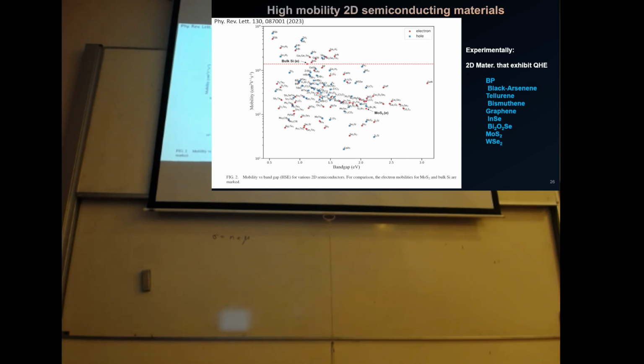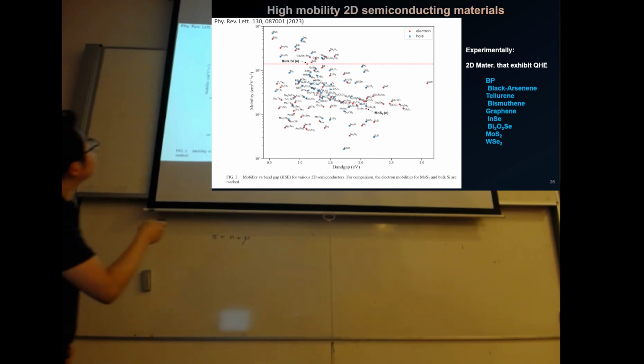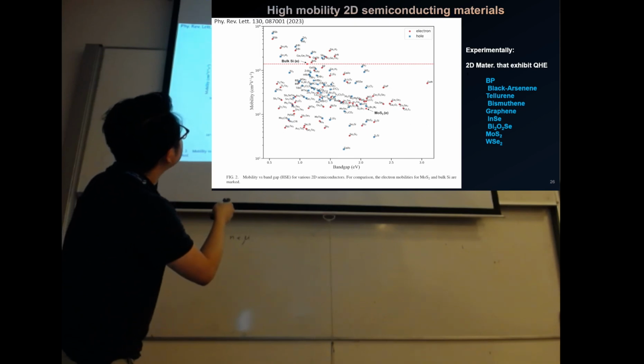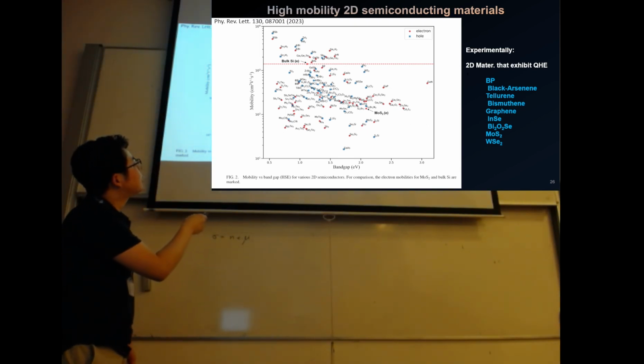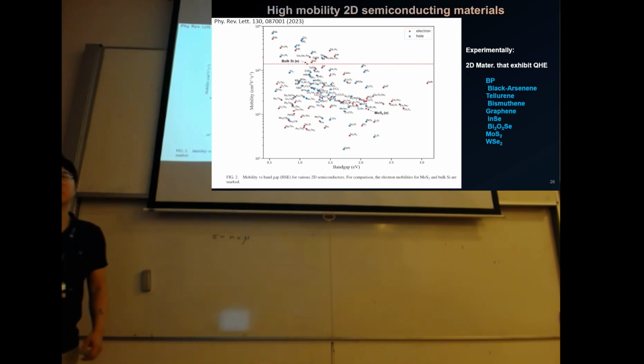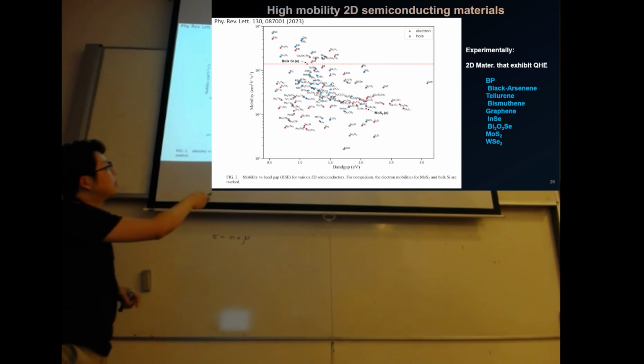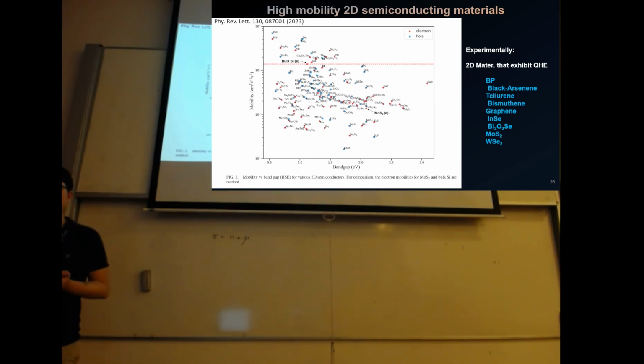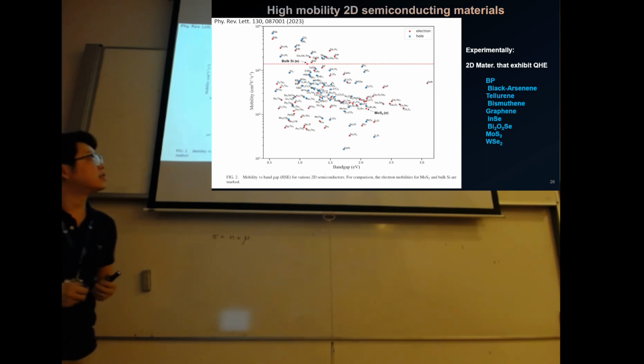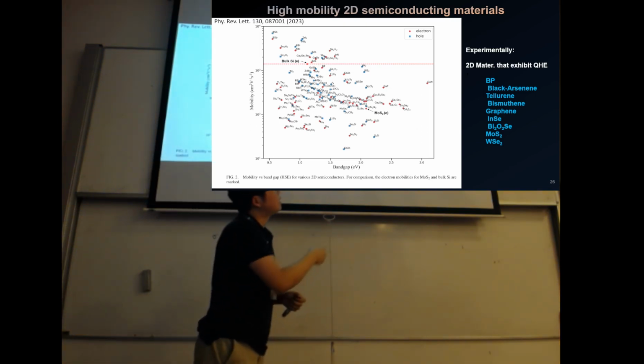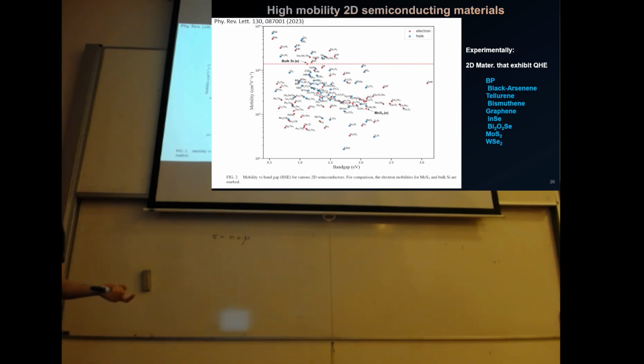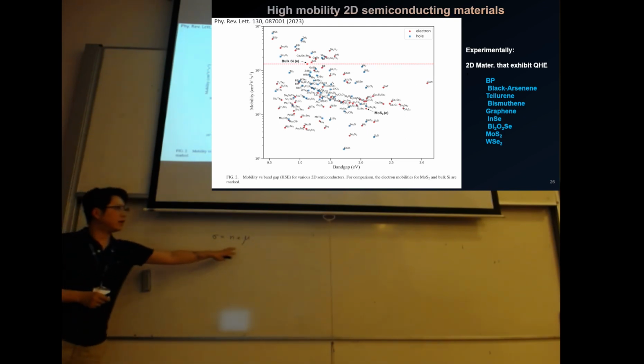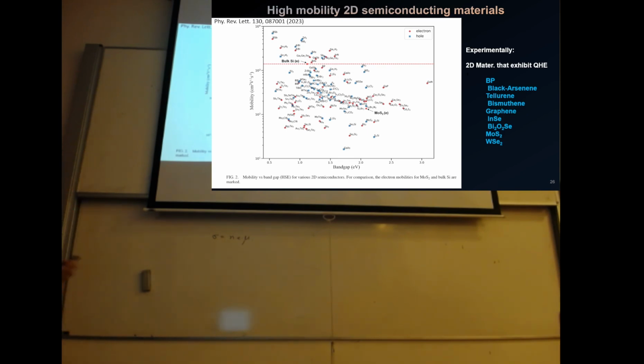And these are basically calculated intrinsic mobilities. This paper was published in 2023, but you can see that some tungsten sulfides and molybdenum disulfide are sitting down there with only 100. Apparently they appear to be wrong, because MoS2, as we'll show you in the coming slides, can have very high mobility at the low temperature limit, up to a few tens of thousands. As long as you have a two-dimensional electron gas and a high enough mobility, which means a long enough phase coherence time for the electrons, they should exhibit the quantum Hall effect.